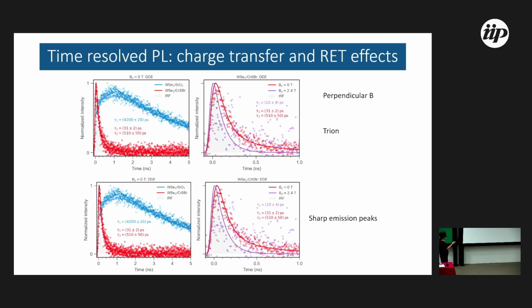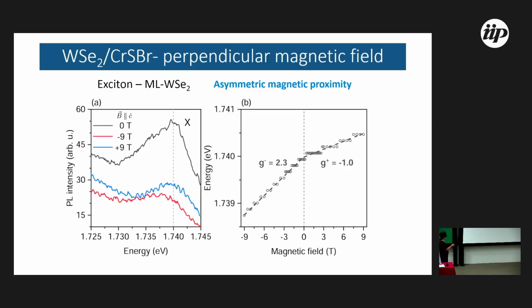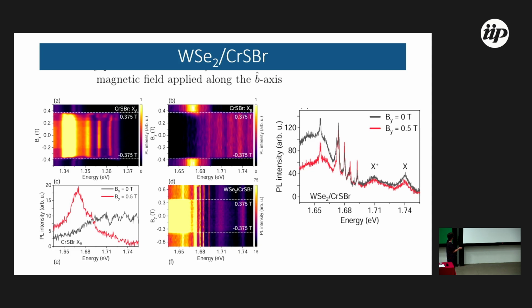So we have also tried to measure time resolved, and we have shown that the times change, which is consistent with this interpretation, but I'll not go into detail. And we also have observed this asymmetric magnetic proximity effect, that we have observed change of g-factors for positive and negative fields. I don't have time to go into detail with other results. So this is the same result for parallel.